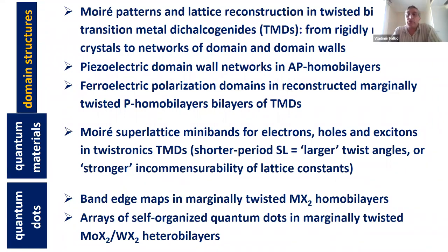For parallel orientation of the unit cells of the crystals, we find a weak ferroelectric charge transfer, which was quite an entertaining exercise, which was also observed experimentally. And after I describe those effects that determine later the band structure of the electrons close to the band edges in the conduction band and valence band, now affected by the periodic strain, by periodic piezoelectric charges or variation of the interlayer charge transfer for electric type, then we can talk about the Moiré superlattice mini bands for electrons and look at the regimes, how these mini bands get narrower upon elongating the period of the superlattice, which can be achieved for homo bilayers by choosing smaller angle of misalignment.